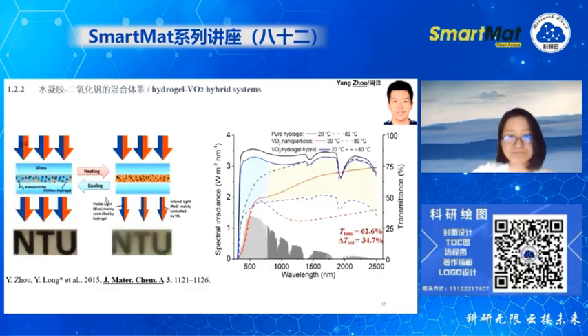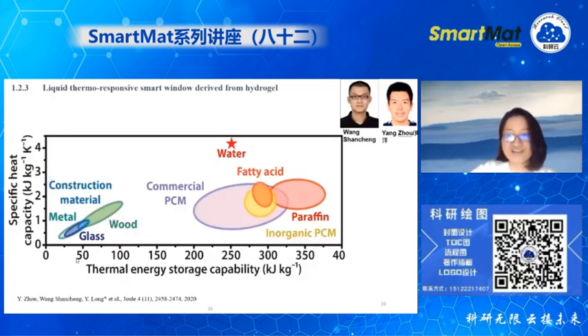Okay, and then the next one, as I said, is a very typical one for material scientists. Once you finish the hydrogel, the organic and the inorganic, the next obvious thing to do is the hybrid. You can see this one is the very typical vanadium dioxide, and this black one is the very typical hydrogel. Once we put these two together, we can radically enhance the modulation. This blue one is the hybrid, and the modulation can reach 34.7. This is definitely one of the highest at that time, I think 2015. This is a very obvious work after we had done a lot of organic and inorganic work.